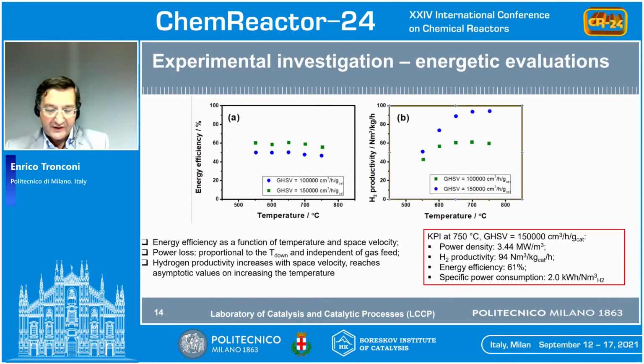Of course, heat losses are an issue in this kind of experiments due to heat conduction across the stainless steel tube wall in spite of the insulation layer that we have included. So we estimated the power losses in our experiment by subtracting the process enthalpy gain from the input power. And we find that the power loss is essentially proportional to the temperature at the outlet of the reactor, but is independent of the gas feed flow, which means that the energy efficiency instead grows with increasing space velocity.